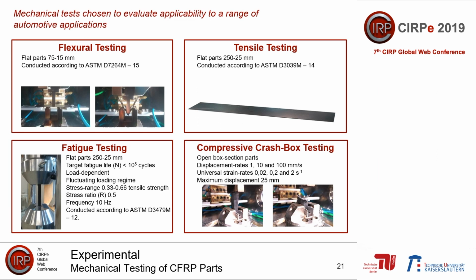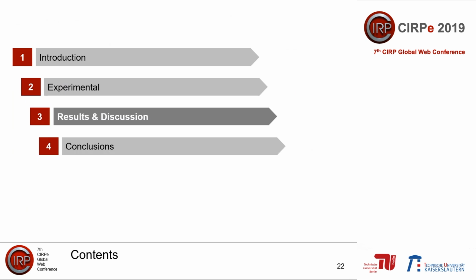Once we formed the parts, we then conducted a range of mechanical tests to evaluate numerous attributes for automotive application. So the flexural testing, the tensile testing, and the fatigue testing, these were actually performed on flat parts. So the same method as shown on the previous slides, but we produced flat parts rather than formed parts for these three mechanical tests. The compressive crash box testing was conducted on the open box section parts as shown on the previous slides, and we have displacement rates of 1, 10, 100 millimeters per second, corresponding to effective universal strain rates of 0.02, 0.2, and 2 seconds to the -1. So let us see the results.